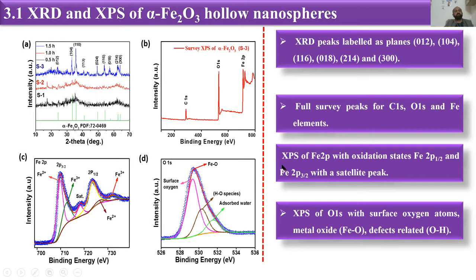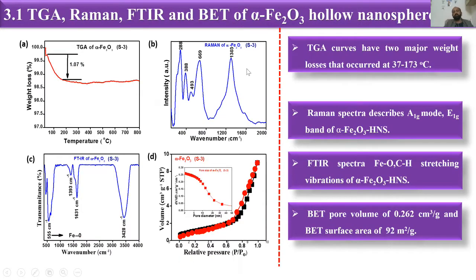We have done the TGA, Raman, FTIR, and BET of our alpha Fe2O3 hollow nanospheres, and again we have got the results. We have got the Raman spectra for our alpha Fe2O3, which matched with the literature. Similarly, we have got the FTIR spectra for our Fe2O3 peaks. And then we have done the BET to find out the specific surface area for our system.